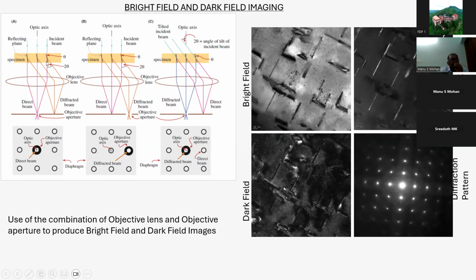Okay, so you see here again the bright beam and the diffracted beam. If you try to focus only the bright beam and use it for analysis or imaging, you are only using the direct beam, that is, the beam which is incident on the specimen and which is not diffracted, which is transmitted through. You produce the direct beam bright field image. Whereas if you use the diffracted beam to form the image, then you call it the dark field.